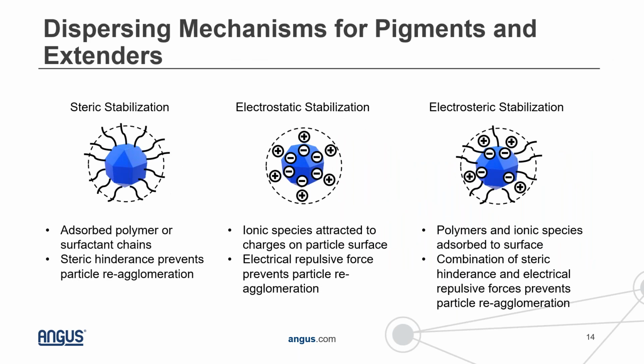So when we consider different dispersing or stabilization mechanisms for pigments, it really comes down to three general categories. The first is steric stabilization. This is the adsorption of polymers or surfactant chains onto pigment particles. If these particles come into contact with one another in solution, the steric hindrance of those polymers or surfactants will prevent the reagglomeration of two particles. So this is one way that pigment particles can be stabilized in solution.